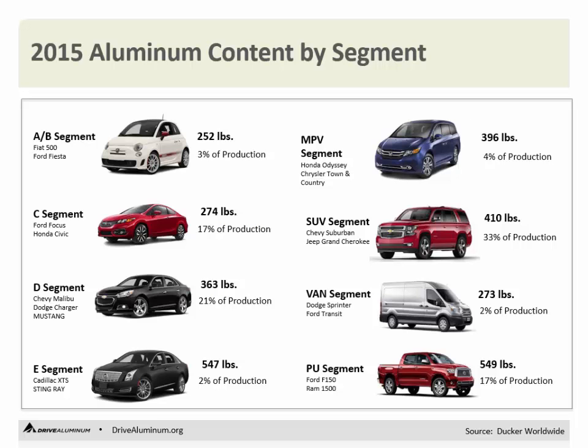When we look at where the aluminum is used, and this is similar to conclusions that we have been drawing for a few years, we look at the amount of aluminum used by vehicle segment. In 2015, the average aluminum content per vehicle is 350 pounds. A and B segment vehicles and C segment vehicles use less than the average content, and typically in these vehicles, the aluminum content resides in the engine, driveline, and wheels. As we look up to larger segment vehicles, D segment, we find a little bit over the average, and in the D segment, we start to see hoods, lift gates, and trunks converted to aluminum.